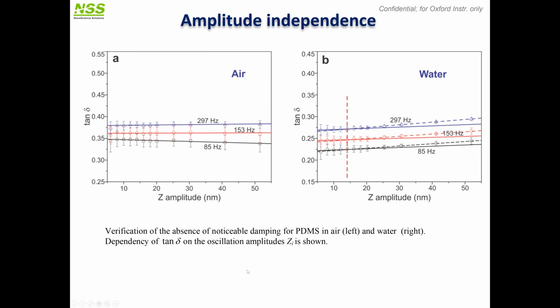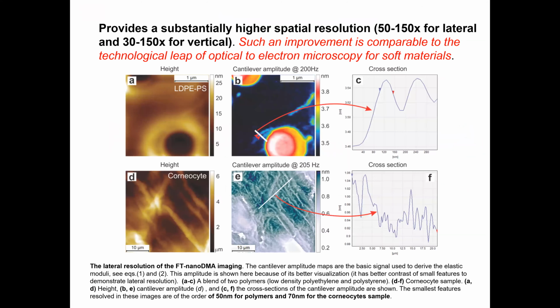Amplitude independence. The equations I showed you before can be analytically solved if, and only if, you have the assumption that the amplitude of your oscillations is smaller than the initial indentation. So that's why it's important to see that we don't really have dependence on the amplitude. In air, we can go to amplitudes of up to 20 nanometers. Here in water, it's better to stop at 15 nanometers. Of course, in water you have more coupling with the surface, so this would be a problem particularly at very high frequency. But again, noise is smaller in water or in liquid, so you can really decrease the amplitude in that case.